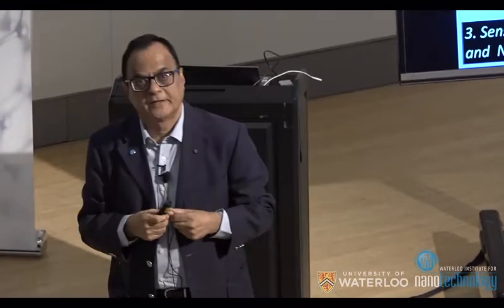Unless you do a suspended graphene, but they have their own problem. Or HBN is what people are trying, and we have also tried. HBN reduces the puddle, but not fully. So it's a very important point in graphene. Any questions?